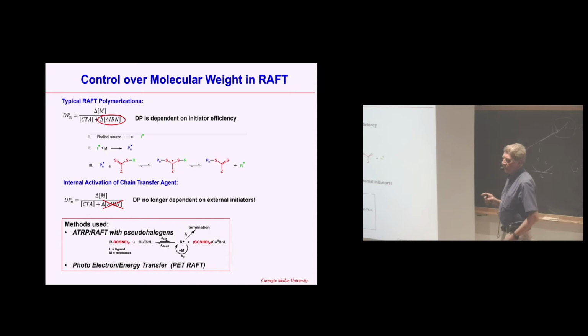One difficulty in RAFT is such that typically you would need to add extra radical in order to propagate these species, because radicals have to be somehow generated. So very often people are using AIBN as a slowly decomposing initiator, which would run this reaction. But also this would give you additional chains. So if you want to make this 5-arm star, you will have a little bit of a 1-arm star generated from this AIBN. So it's a question how much you can tolerate, or how can you generate them spontaneously.